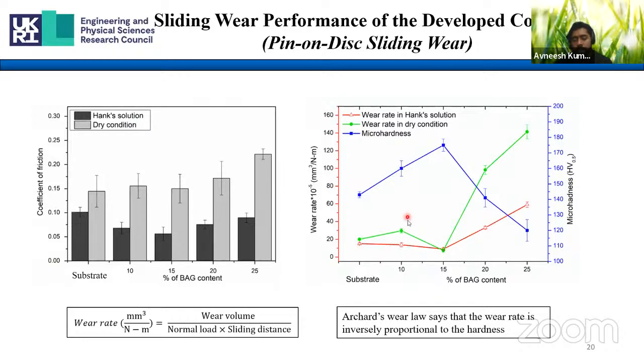The reason for this can be that the substrate we used was mirror polished, so the initial wear in that case was minimum. But in these coatings, which were as-sprayed coatings, we had some peaks and valleys. Those peaks were hard enough, but because of high concentration of stresses, severe plastic deformation of those peaks occurred, and the initial wear caused the high wear rate.